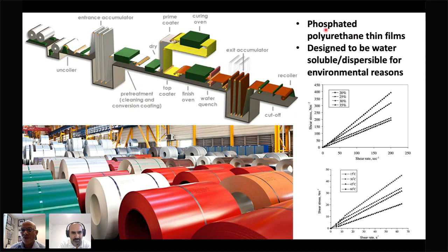So the idea that I had at that point is, why can't I eliminate this process using a phosphated polyurethane thin film. And so then I went to grad school to do this. And as they say, the rest is history. I was able to design a water-soluble and dispersible polyurethane thin coating for addressing this environmental concern, which otherwise is a carcinogenic material.